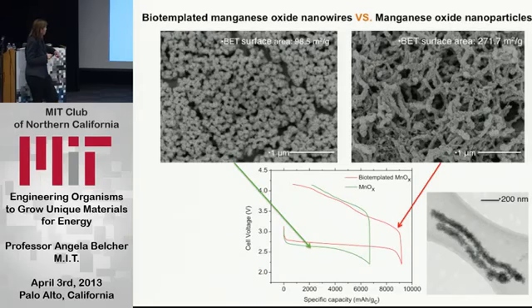And what Daehyun was able to do was grow manganese oxide nanowires and make this higher surface area material. And then she showed that this is just the manganese oxide without the virus. And they're looking at cell voltage versus capacity here. And this is the non-biologically templated material, and the biologically templated material increases it by about 40%. In this case, we think that what the biology is doing is just changing the architecture, increasing the surface area of this material. But it was a start, and we didn't want to stop there.